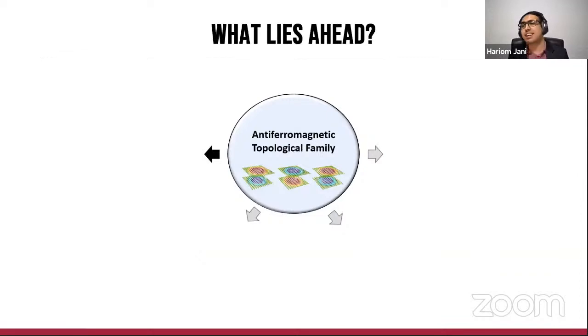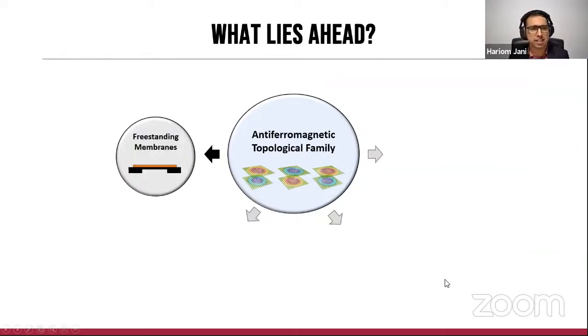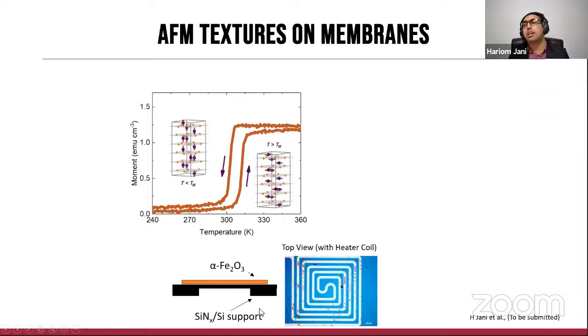Now, given that we have looked at the discovered mechanisms and how we can control them, I would like to spend the last 10-15 minutes discussing what really lies ahead for this body of work. And I would first like to start off by discussing our very new results in freestanding membranes. And this is actually achieved by having freestanding Fe2O3, which is then transferred and supported on silicon nitride. And this is very critical for us to do any transmission geometry experiments where a substrate is not blocking it.